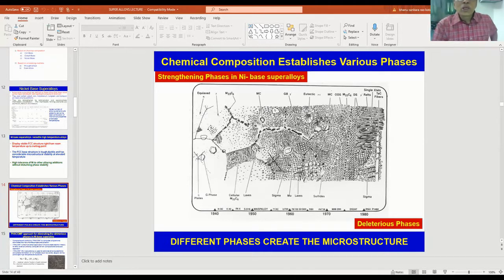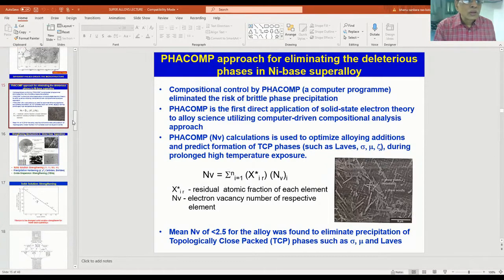So most importantly, what I wanted to say is chemical composition establishes various phases. Different phases create the microstructure. That's why the microstructure plays a very, very important role. If you want to have a desired microstructure for long-term service at elevated temperatures, the composition has to be controlled very properly. The undesirable TCP phases have been controlled in superalloys by an approach known as the phase computation approach.